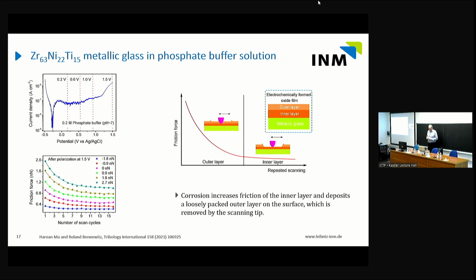Now to this metallic glass. What you see on the upper left is a current density versus potential curve. This is a so-called polarization curve. And what you can see here essentially is that there's a so-called passive regime which extends to, let's say, 0.5, maybe a little higher volt in potential. And then it starts oxidizing, and then you have a transpassive regime where the whole thing starts oxidizing, and if you wish, it starts bubbling. I mean, it's not really bubbling because it's a metallic glass, but a lot of things happening.